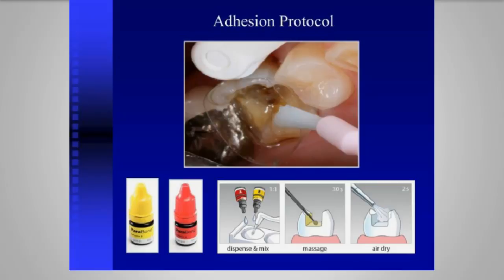You mix them fresh. Under no conditions do you open up these caps until you actively are placing the material, because otherwise you lose your chemistry and the volatility of these adhesives. You mix them together, you massage it in for 30 seconds, and then you lightly air dry.